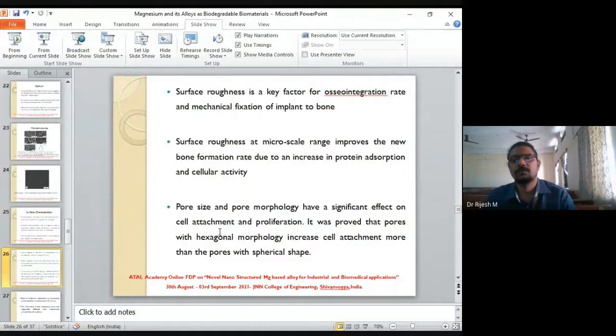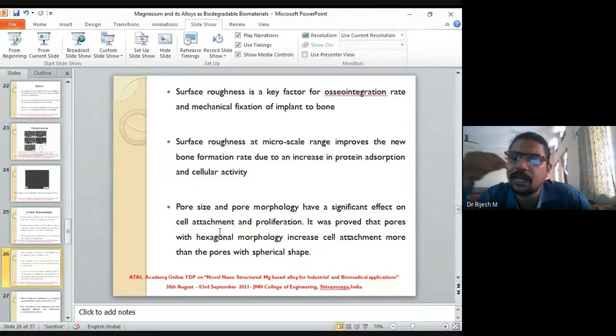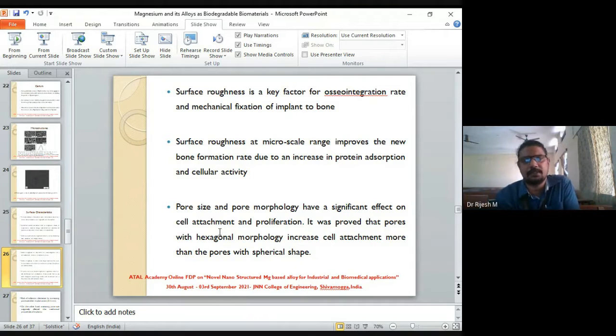So surface roughness is a key factor for osseointegration rate and mechanical fixation of implant to bone. So we deliberately make some rough surface on the surfaces. That's why I told you a powder metallurgical product with an amount of porosity on the surface is actually very helpful for bio implant. Surface roughness at microscale ranges improves the new bone formation rate due to an increase in protein adsorption and cellular activity. Got it.